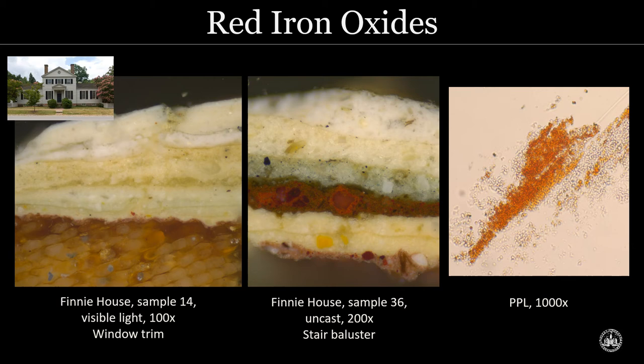So here's an example of a red iron oxide primer. This was taken from some interior woodwork at one of our buildings called the Finney House, which we believe dates to the late 18th century. And when I conducted the paint analysis, I found that a red iron oxide primer was used throughout. So we can see it here in this paint cross-section. Here is the wood substrate.